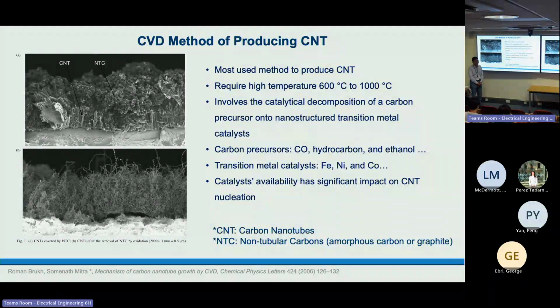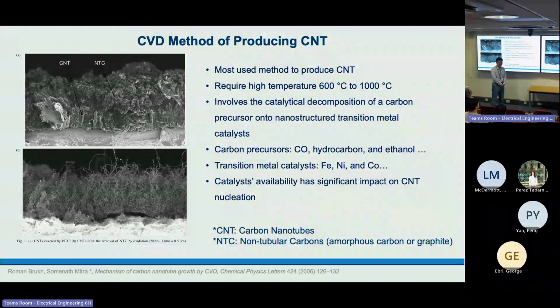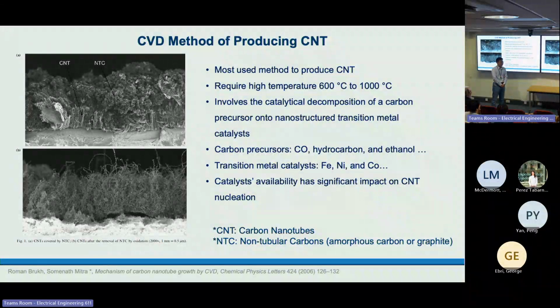In CVD, most of the catalysts are in the form of nanoparticles, right? Yes. So if that's the case, maybe changing the topography of the iron wire can have a huge effect on how much of the CNT can be formed on the working electrode. Maybe making it more porous is better. Yes, that's a very good point. In the future, we would like to investigate if we can produce some nanostructured surface on the iron electrodes. Maybe in that case, it's better for the nucleation of the carbon nanotubes. Definitely, thank you.